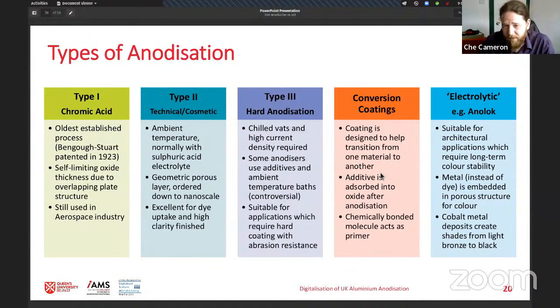In response to that, we see in the modern trade, some anodizers will use additives and an ambient temperature bath to achieve hard anodization. It's a little bit controversial in the industry, though. Some people would claim that that's not really hard anodization, while those undertaking the process would claim that you should just look at the final properties of the film. It's just something to highlight. And this, as the name suggests, is suitable for applications which need that hard coating with abrasion resistance.